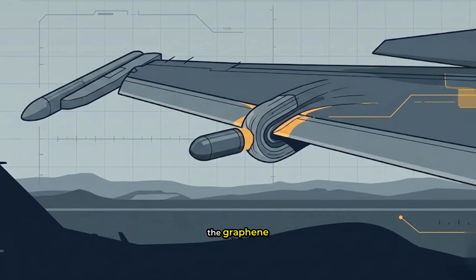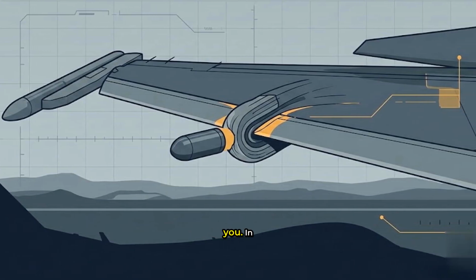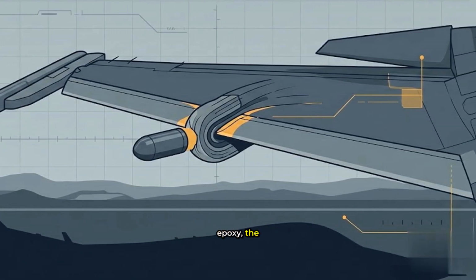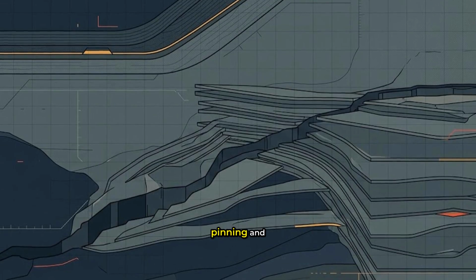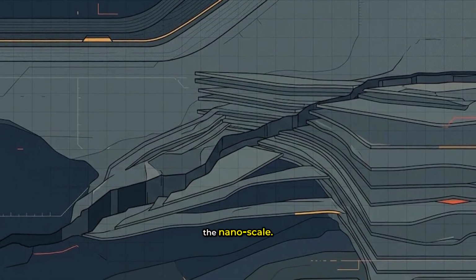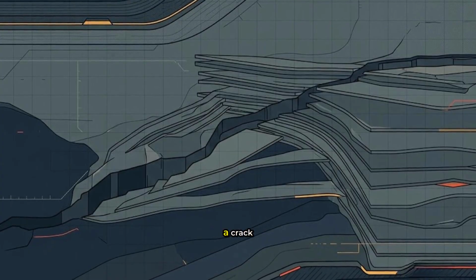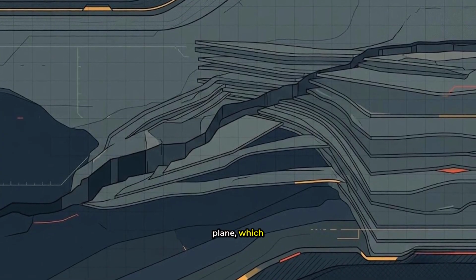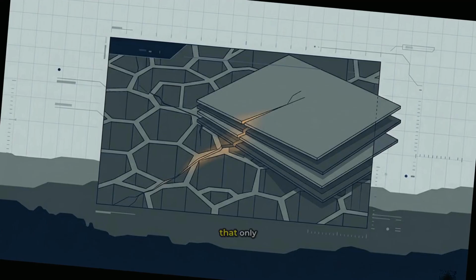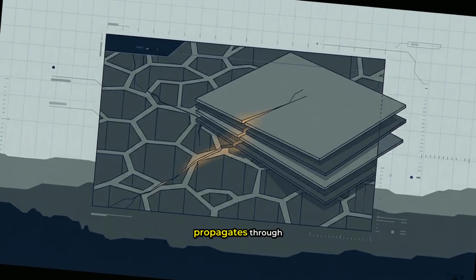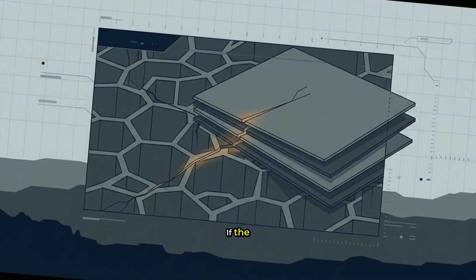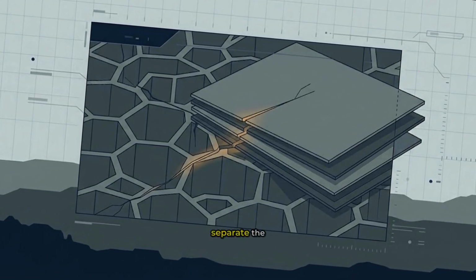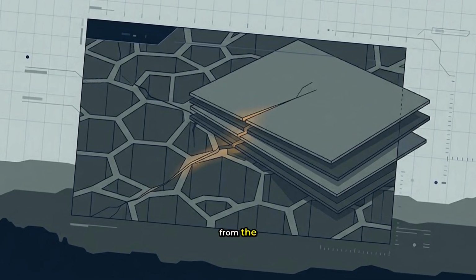Here is what the graphene enthusiasts do not tell you. In a graphene-reinforced epoxy, the improvement comes from crack pinning and deflection at the nanoscale. The graphene sheets force a crack to twist and change plane, which absorbs more energy. But that only works when the crack propagates through the matrix. If the impact shear is strong enough to separate the graphene layer from the epoxy itself, that mechanism fails entirely.